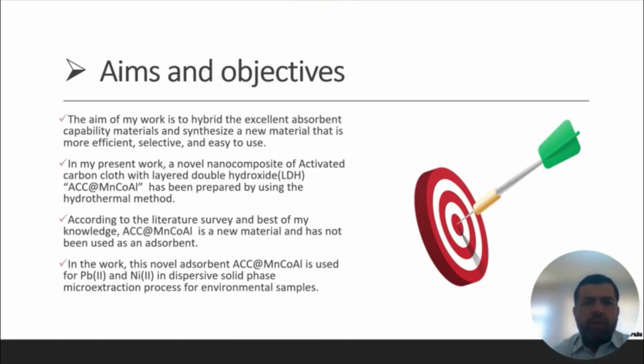The aim of my work is to hybridize excellent adsorbing capability materials and synthesize a new material that is more sensitive, more efficient, and easy to use. In my present work, a novel nanocomposite of activated carbon cloth with layered double hydroxide (manganese, cobalt, aluminum) has been prepared using a hydrothermal method. According to the literature survey and to the best of my knowledge, this one is new and has not been used as an adsorbent. This material is used for lead and nickel determination from food and environment.